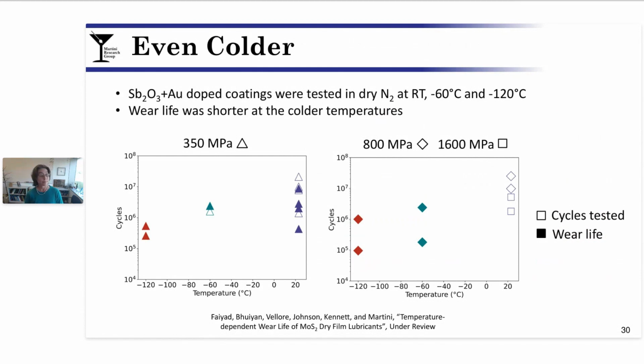What I'm showing you here is number of cycles versus temperature, where the solid symbols indicate the wear life was reached, and the hollow symbols indicate the test was stopped prior to reaching the wear life. The left figure is for a lower pressure condition, the right figure for a couple higher pressure conditions. But the main upshot of these plots is that as we go from room temperature to -60 to -120, the wear life of these coatings decreases. Again, this type of information, this data is invaluable as we try to take MoS2 as a dry film lubricant to an enabling technology for space.